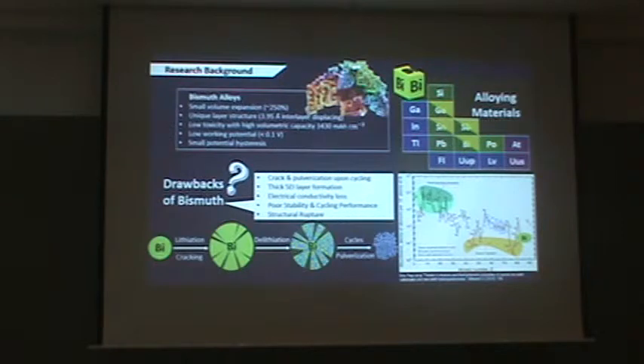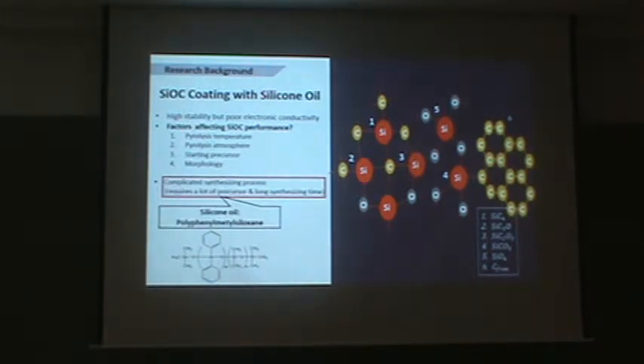But the issue is that the structure of carbon-based material is very rigid, so it tends to break or collapse upon cycling. Thus, we introduce a coating of silicon oxycarbide from silicon oil. The issue in silicon oxycarbide coating is that most of the precursors used are very complicated and the process takes a long time. That's why we suggested using silicon oil in a simple process just by pyrolysis.